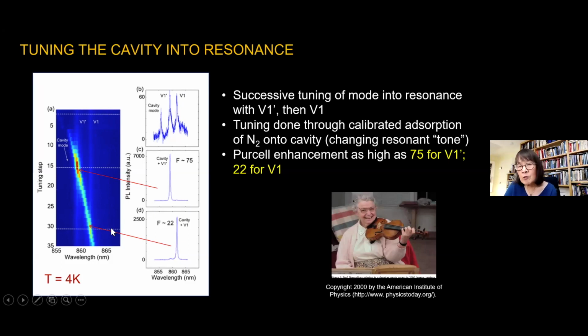But the purpose of showing you this diagram is that we can take this beautiful instrument that we've made, humble though it appears, and we can change its resonant frequency by adsorbing gaseous condensate onto the cavity. So by doing so, we're changing the resonant response of our instrument. And as we do it, we change this cavity mode, the response, so we shift it to be in frequency resonance first with V1 prime and then V1. And what you can see as we do that in succession, we can get this Purcell enhancement of as high as 75 for one of these transitions.